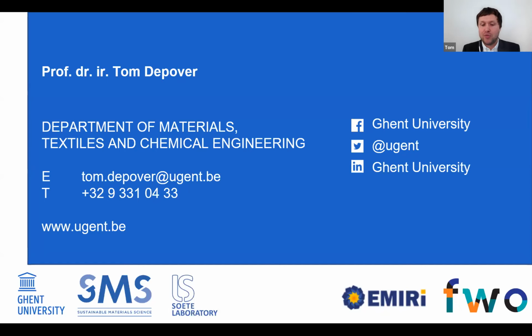However, this is being shown on pure steel, where the interface for the surface is the steel microstructure. When you put a coating on top, this is a totally different story. There is no research yet done on the effectiveness of a coating and the inhibition of these gas impurities, how they can act. Many people claim that with polymer types of coatings, for instance, these small molecules can penetrate over a long time of exposure. So it can be a possibility, but it's not for sure yet.